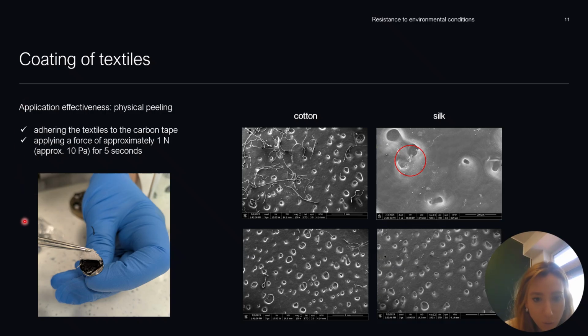Here are also not only the picture of the peeling, but in some cases the scheme of the procedure. As illustrated in the pictures, only one detached graphene oxide sheet was observed on the silk sample after the peel test, whereas no nanocomposite detachment was detected on cotton. Here are the two pictures.